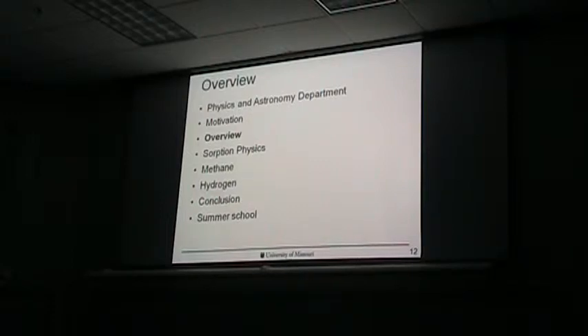So now I'm giving a small overview about materials which are out here in the world, which are used or at least studied for this methane adsorption. This one shows on the x-axis the gravimetric storage capacity. So that means how much gas they store per kilogram of material, and the volumetric is on this axis. It means how much it stores per volume. And you have these yellow circles, squares. These are all materials we make in our lab, which we produce and analyze in our lab.